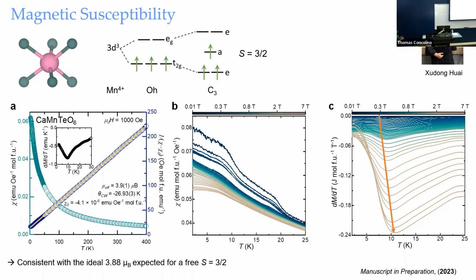However, that actually gets suppressed in higher field. Now, you take the dχ over dT as a function of temperature. What we're seeing is that the transition temperature can increase as the magnetic field increases, which means we're onto something here a little bit, right? Because typically we would expect the other way around. So that means maybe we would have some field-induced magnetic phase transitions.